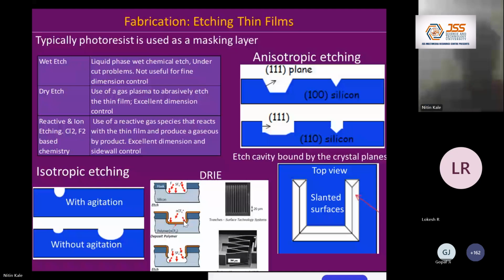The dry etch could also be due to reactive ions, for example, chlorine and fluorine based chemistries, or even bromine based chemistries in certain cases. There are certain newer etching techniques which are used to etch only silicon substrate. They are, for example, the deep reactive ion etching. You could get either isotropic surfaces or anisotropic surfaces. Anisotropic means directional control you have as far as the etching goes. And you can have very interesting patterns of the material that you so desire.